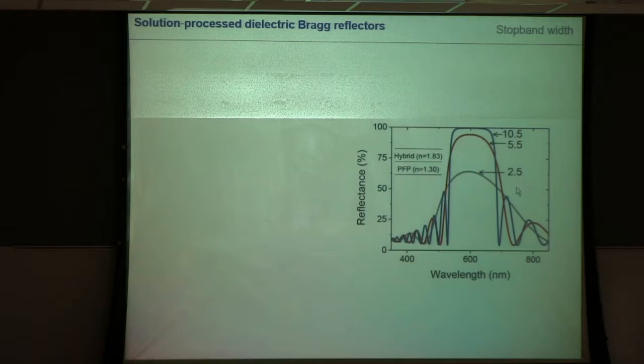And I have to say, these are really measurements on mirrors that we made, so it's not calculations. So we can tune the color that is reflected of our photonic crystals. And that's shown here, pictures of mirrors that reflect the blue, the green, and here more the orange, yellow. For many applications, it's not only what wavelength is reflected, but how broad. So I will show you examples, for instance, in heat management, where we want to reflect over a pretty broad wavelength regime. This can be done by really increasing the refractive index contrast a lot. That has also the advantage, the larger the refractive index contrast, the fewer periods you need to really reflect all the light in that regime.